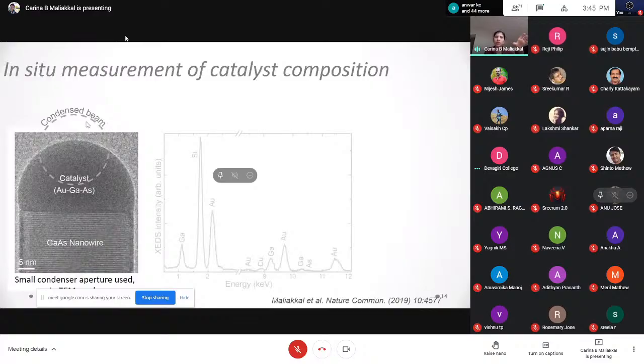But during the growth, it can be very, very different from after the growth, because growth is happening when there is a gallium precursor, arsenic precursor, and at a high temperature. Once you've cooled down, the system is totally different, and you can't understand what the catalyst composition was during growth by doing an ex situ or later research. So what we did was we studied for the first time the catalyst composition in situ, while the wire is growing, in the same instrument.